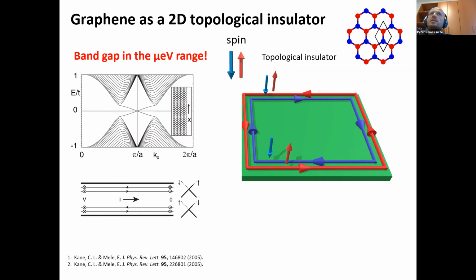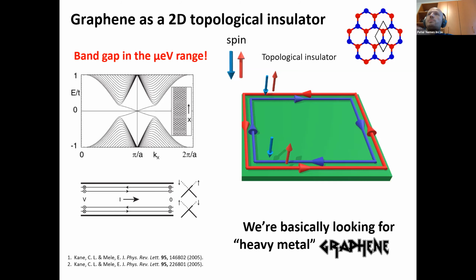The problem in this case is that in graphene, due to the very small spin-orbit coupling of carbon, you get a band gap in the micro-eV range. So what we're basically looking for, if we want to explore 2D topological insulators, is some kind of heavy metal version of graphene, if you don't mind the pun.